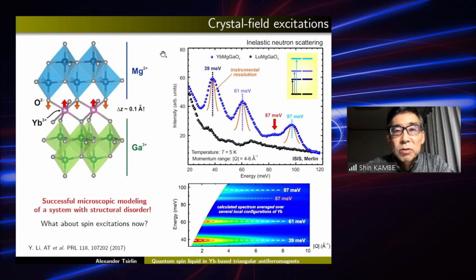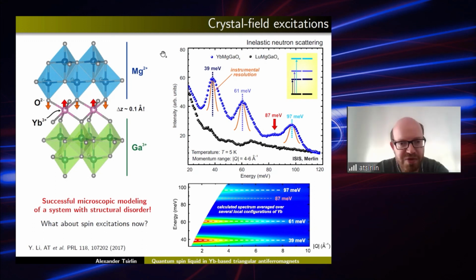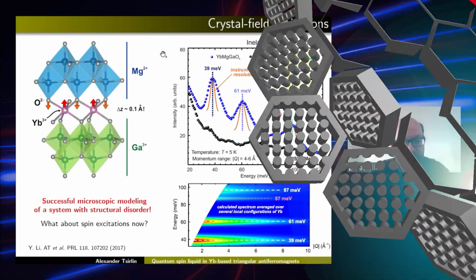Any other comments or questions? There is also a question in the chat, so maybe I just read it. For the sodium compound, do you have indications from muSR for a disordered versus ordered ground state? So for the sodium compound, we did muSR, and there are no signatures of magnetic ordering, like there are no oscillations in the spectrum. There are some features which are not entirely clear to me, like there are 2 relaxation rates for some reason, which is something that people see rather often, maybe at different muon stopping sites or something. But yeah, this is one peculiarity that we saw in the muSR, but certainly no static fields.